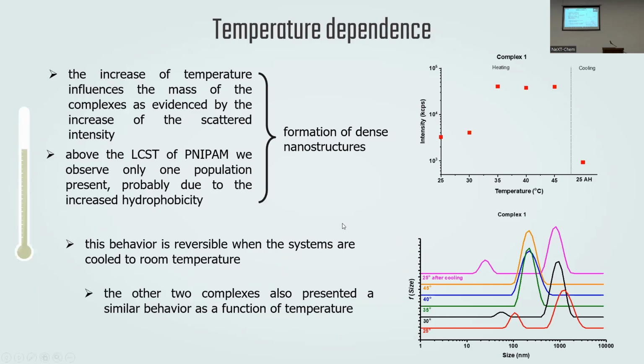The temperature dependence was also investigated by dynamic light scattering between 25 and 45 degrees Celsius. So we wanted to confirm that the thermoresponsiveness of the synthetic polymer isn't affected by the complexation with chitosan. As we can see in the first figure, which shows the intensity of the scattered light, the increase of the temperature influences the mass of the complexes, and this is evidenced by the increase of the scattering intensity above the LCST of PNIPAM.